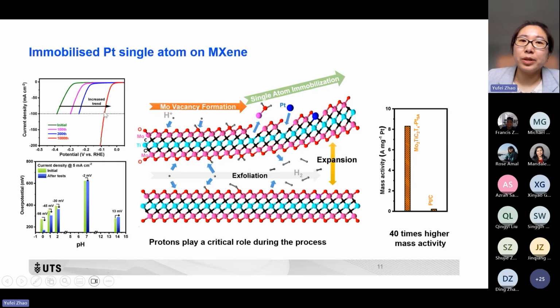Based on the experimental result, we have proposed the mechanism for the MXene exfoliation and also for the single atom immobilization. During the HER process, the proton will interact with the oxygen termination here, because from previous publications or DFT calculations, they have confirmed that the oxygen termination is normally the active site of the MXene for the HER process. So it should interact with the oxygen first and produce hydrogen.